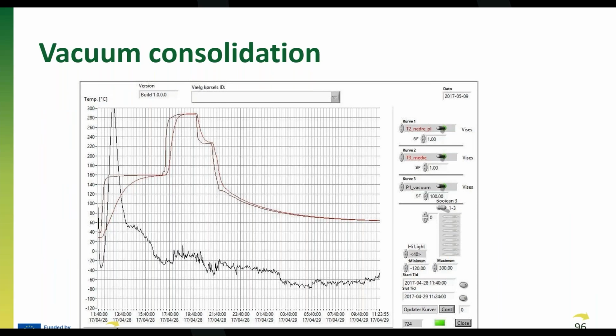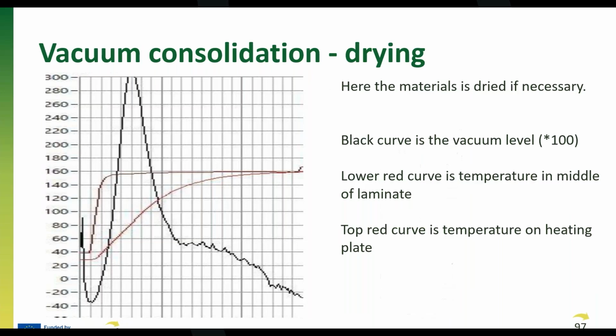Here you have a real recording of a thick laminate that we made. But I would like to cut it down into sections, and then you can take the next one. Because the first one, as I said, you can incorporate is drying. And here you see we put it on a temperature of 160 degrees for this system here. And that's the first red curve you see. And as this one is a very thick laminate, you could see in the other lower red curve how long time it actually takes to gain the same temperature of the materials as you have put on the outside.